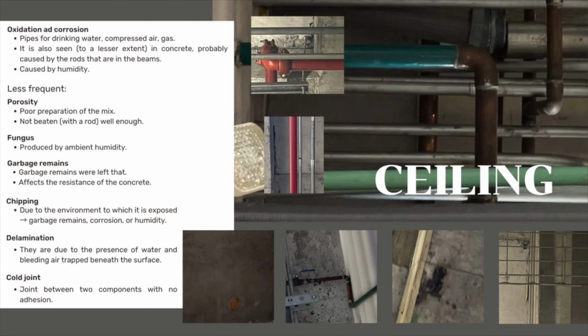And, to a lesser extent, we have porosity, which is usually caused by poor preparation of the mix. If it is not beaten with the rod well enough, then it doesn't compact well, leaving spaces or pores in the concrete. The fungus is produced by the humidity of the environment. In addition, at the time of pouring, garbage remains were left that also affected the resistance of the concrete, probably causing cracks and the concrete to fall.